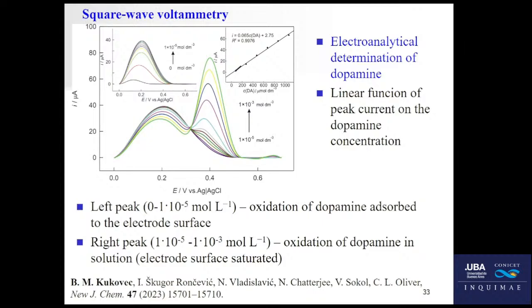As we explain it, up to 10^-5 there is a peak current increase because the surface of the electrode is still available, but at 10^-5 it is saturated, so it doesn't increase more, and the dopamine starts to oxidize, but not the one at the surface of the electrode, but the one in the solution. If you look at the linear function of the peak current and dopamine concentration, it's shown here. This one is for the lower concentration peak, and this one is for the higher. So both peaks can be used for the analytical determination, depending on the concentration range.